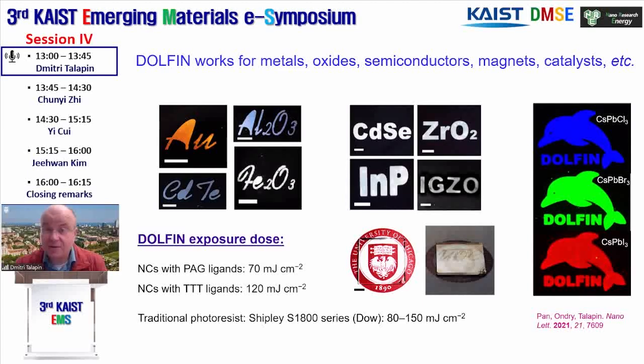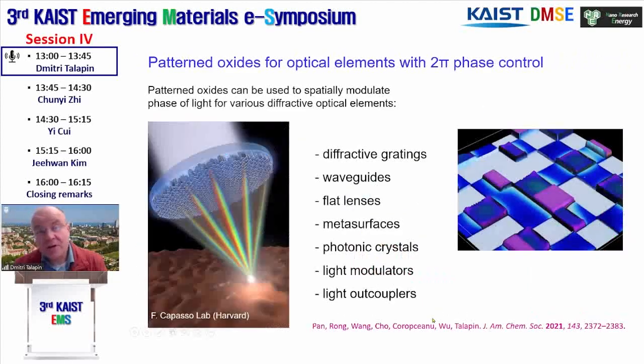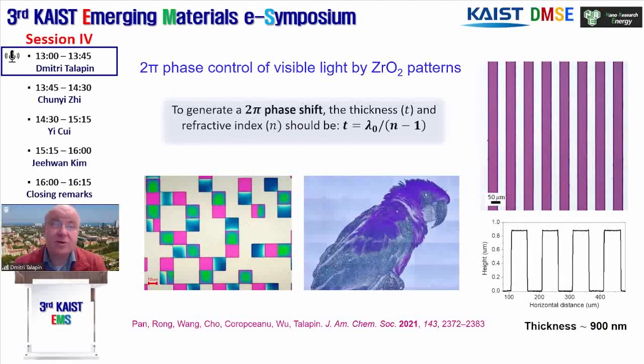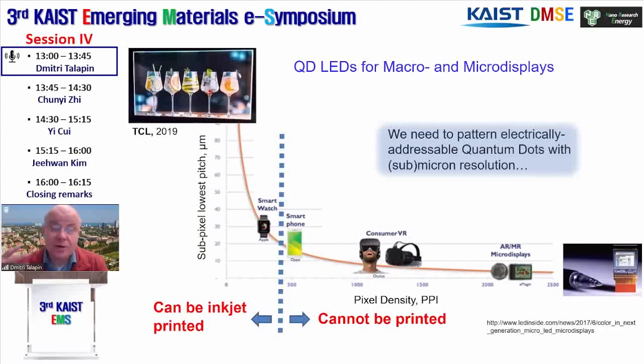But overall, this DOLFIN approach, this engineering of surface using photochemically active surface ligands, allows you to pattern metals, oxides, semiconductors, perovskites, pretty much every material that can be made in the form of nanoparticles, with exposure dose very comparable to the exposure dose of commercial photoresists and the same resolution. So you can do it, for example, for patterning metasurfaces with oxide nanoparticles, so you can control the phase of light. You can also pattern active micro LED or LED pixels, and that is important. Here again, as a word of caution, we need to be careful understanding where the challenges are. If we talk about large displays, where the subpixels are about 100 micron by 20 micron, I believe those pixels can be ultimately inkjet printed.